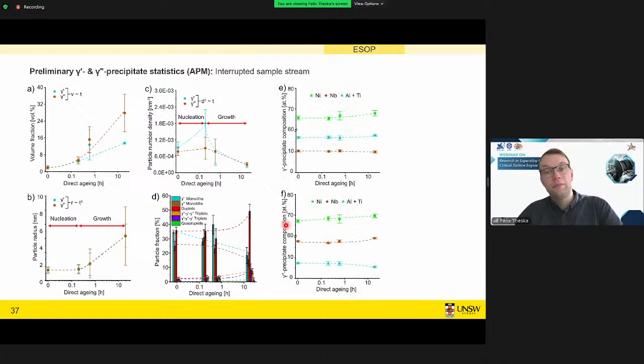While we have this Atomprobe data, we can also extract the chemical composition of these particles, and we see in figure E, gamma prime is enriching over time with nickel and aluminum and titanium. Now that's expected, but if you look at gamma double prime, it's doing something interesting, where it's enriching in nickel and niobium, but it's also rejecting aluminum and titanium back into the matrix.